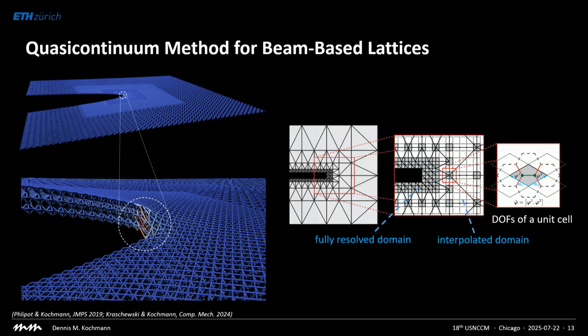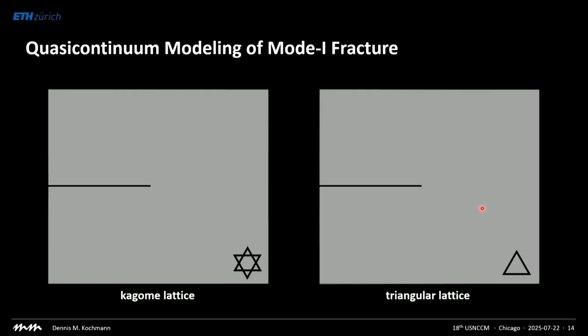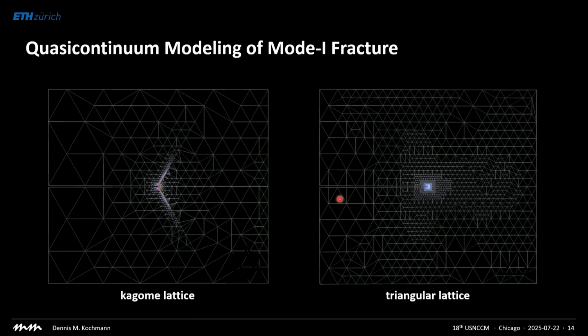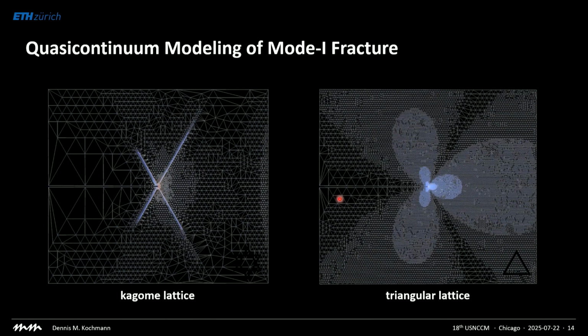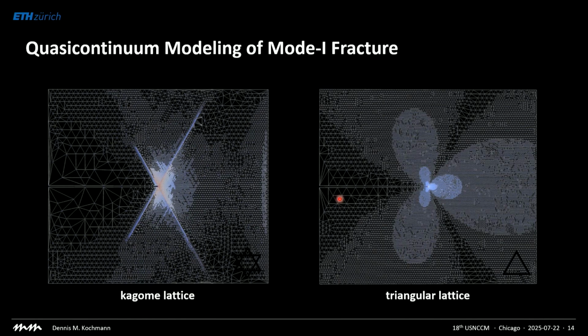Our community knows how exactly this works. So here are two examples in 2D to begin. A simple Kagome lattice on the left, a triangular lattice on the right. The crack is where you can see it. If I now load this remotely and turn on adaptive remeshing, this is what happens. And you see one interesting thing, which is apparently the remeshing scheme in these two cases looks very, very different. Why is that? It's, of course, not an artifact. It's a feature. It's physics.